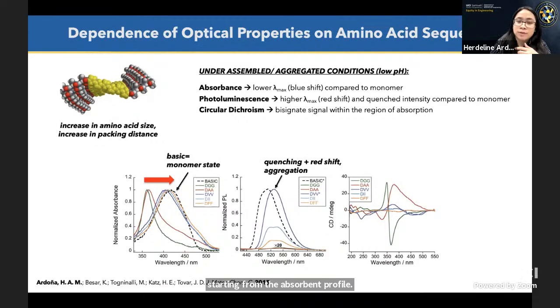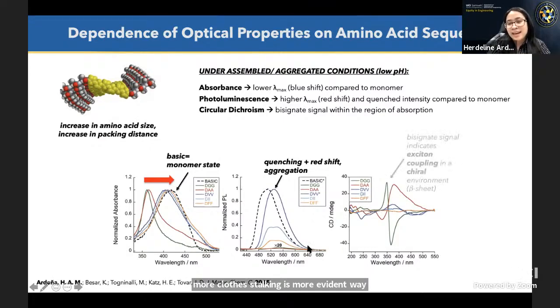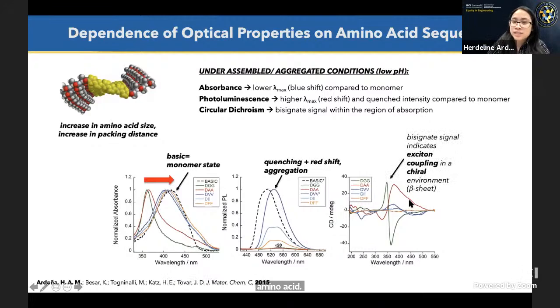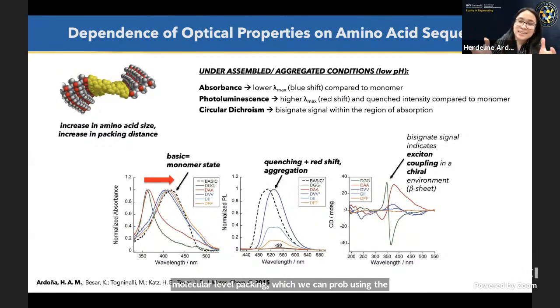And when we look at the photoluminescence, we can see that the quenching, which represents more aggregation or closer stacking, is more evident with the smaller amino acid. And in the circular dichroism, we see a bisignate signal that is more intense only for the smaller amino acids, glycine and alanine. This shows that even in the molecular-level packing, which we can probe using the optical properties, we can see these changes and tune these properties, even though it's the same family of monomers, just by doing simple amino acid sequence differentiation.